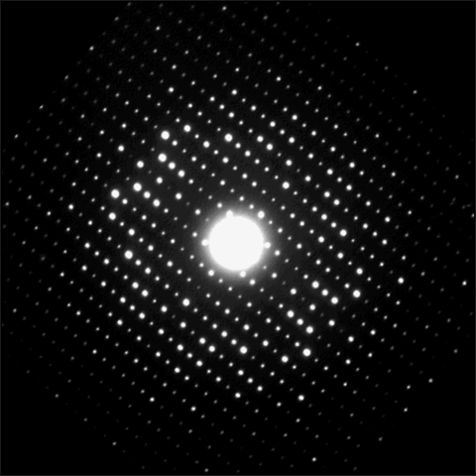On the other hand, ED patterns of inorganic crystals often have a high resolution, with interplanar spacings with high Miller indices much below 1 angstrom. This is comparable to the point resolution of the best electron microscopes. Under favorable conditions it is possible to use ED patterns from a single orientation to determine the complete crystal structure. Alternatively, a hybrid approach can be used which uses HRTEM images for solving and intensities from ED for refining the crystal structure.